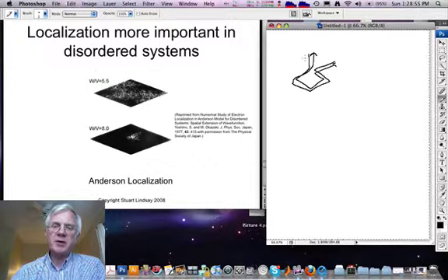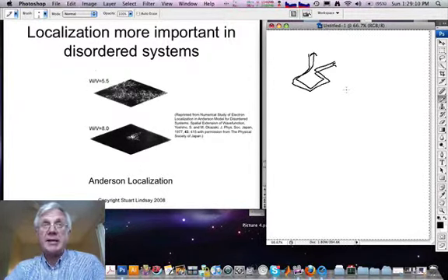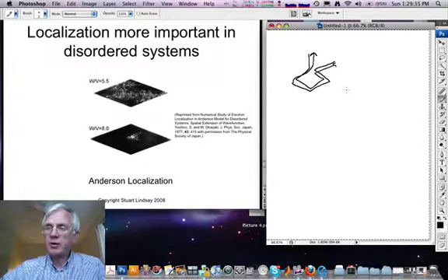Because of Anderson localization, one observes some quite unusual phenomena, particularly in nanostructures of low dimensionality like wires. The effect of thermal energy, heat, is usually to increase the resistance of a material. A hot light bulb is very much more resistive than a cold tungsten filament. However, in nanowires that are disordered, one frequently observes a phenomenon in which the resistivity decreases with increasing temperature.